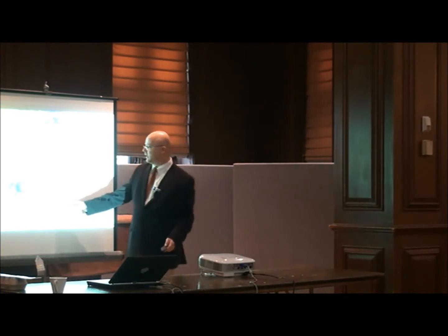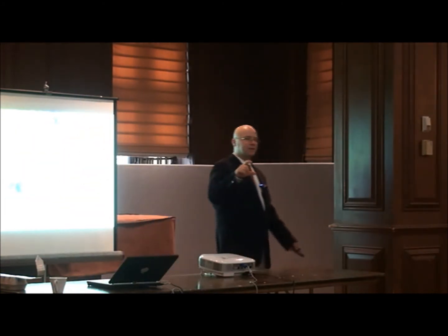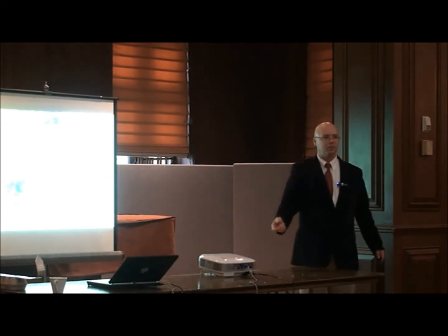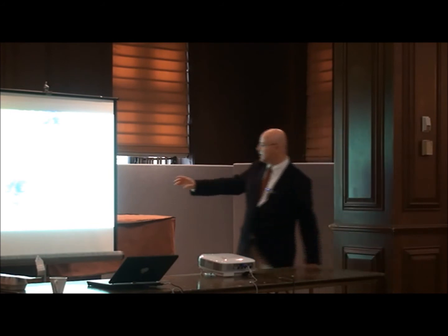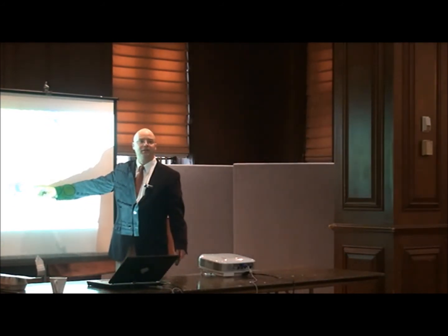If we want to go at the 45-degree angle, now the sampling interval, the minimum distance between points that I've actually measured, has become the square root of 2 times my sampling interval, right? So I've got to get the angle. If I pick another angle and I want to only use a measured point, now I'm at this angle. If I want to use only another point and I want to get another angle, I'm out here.